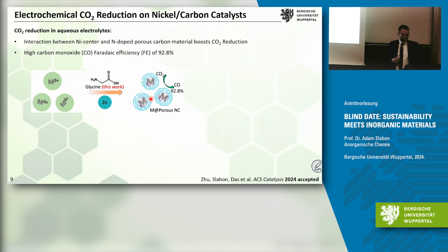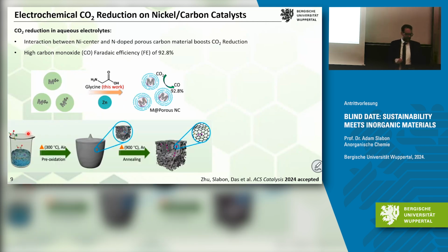How do we do it? We start first with a simple solution. We add it together and make a pre-oxidation step under air. Then we increase the temperature under argon to 900 centigrade, and the zinc leaves our matrix, and we are left with a mesoporous material with a high surface area.